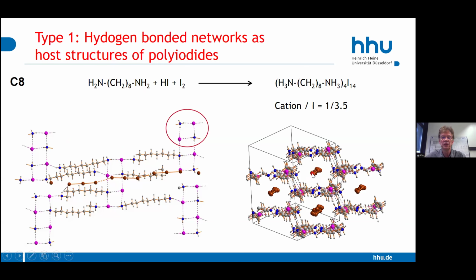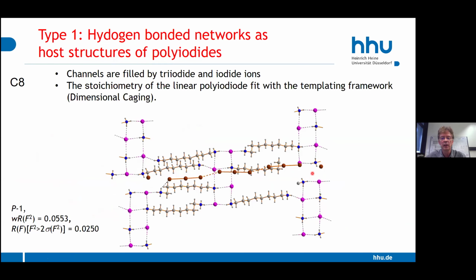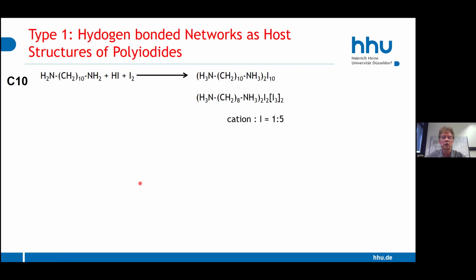If we look into detail into this polyiodide, we find out, okay, it's constructed of an I minus, and then 3 times the I3 minus, and then it starts again. So this is an interesting new polyiodide, which is fitting with the length of this framework. You see, it starts from here to here, and then you have this sequence again. So the idea is now simply to change the length of these organic molecules to get other polyiodides. And of course we did.